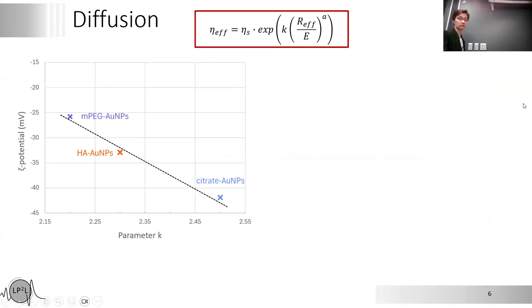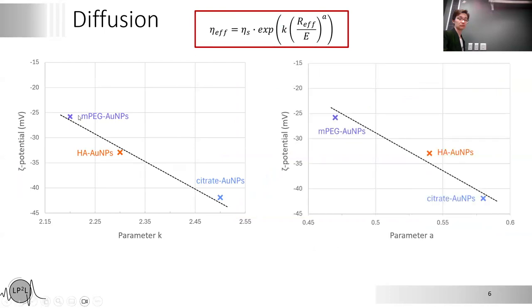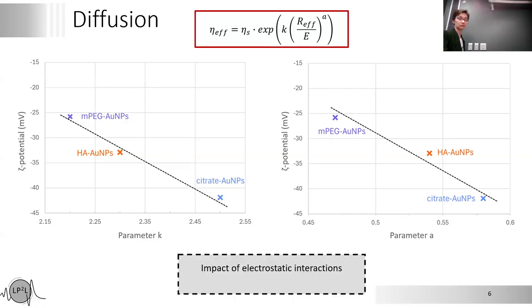Then, I was interested, because of my application for the vitreous, in using different coatings for my nanoparticles, because for biological applications we want biocompatibility and sometimes also specificity. So for biocompatibility, I use polyethylene glycol and also hyaluronic acid coatings. And as you can see, it seems that there is a correlation between the zeta potential of our coatings and the value of the parameters K and A, which highlights the importance of electrostatic interaction, and we need to take it into account in this model.